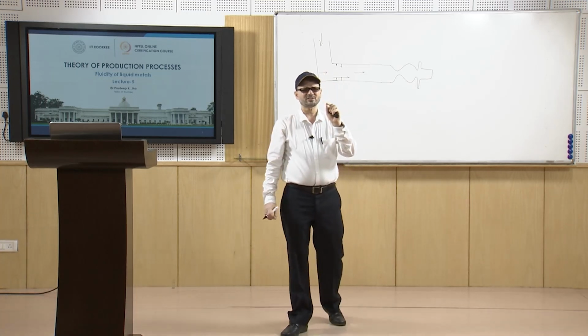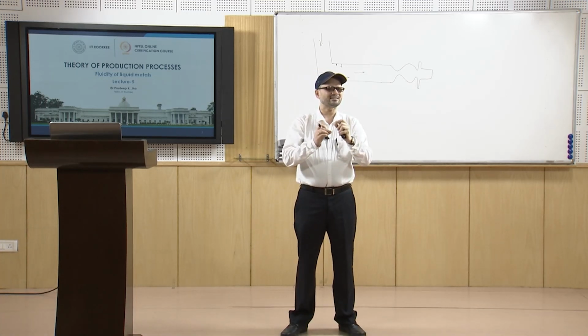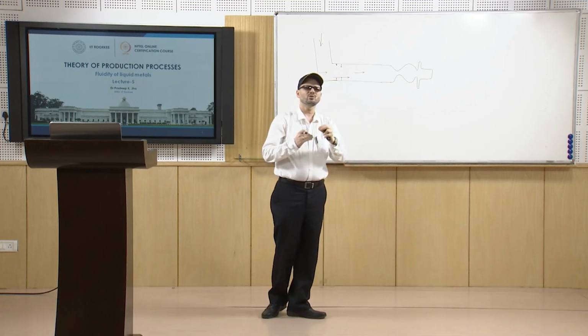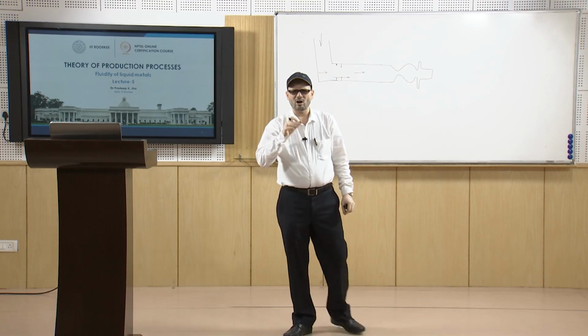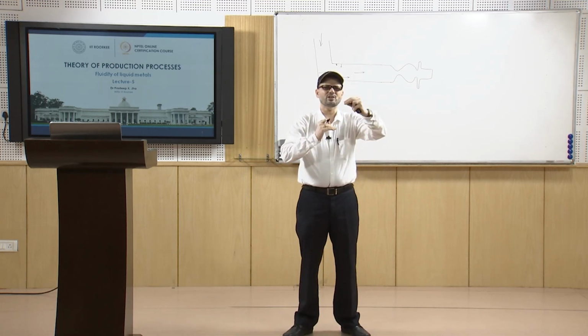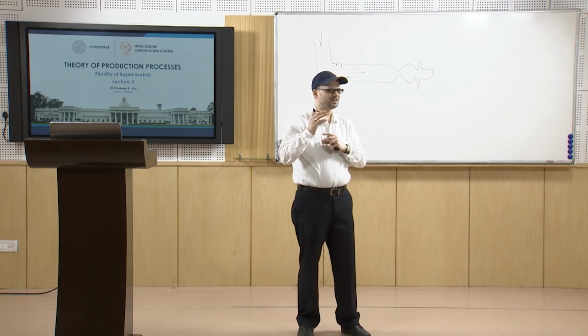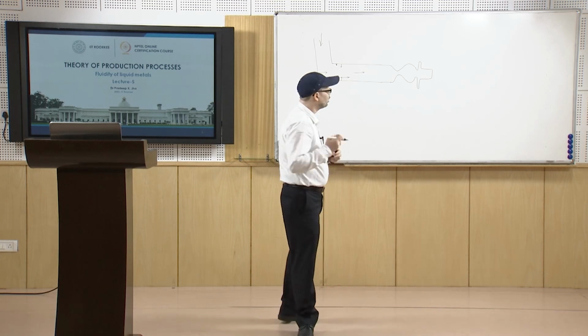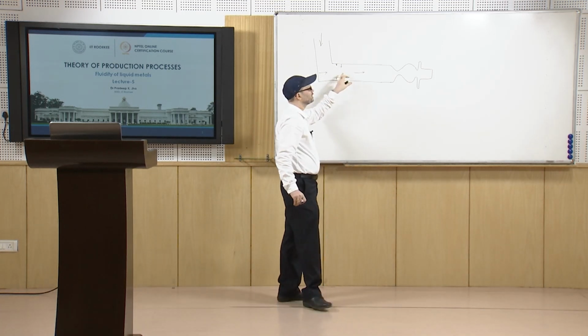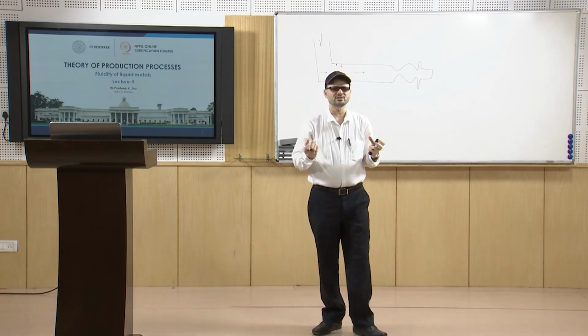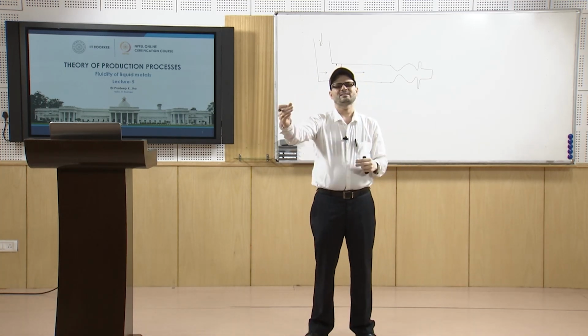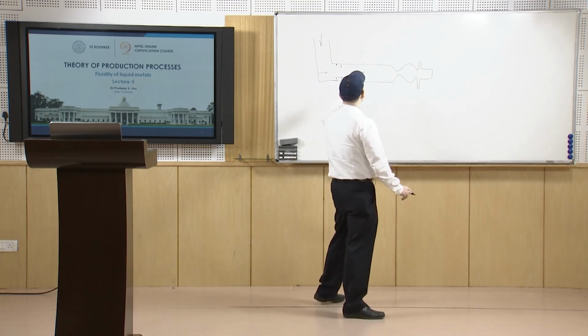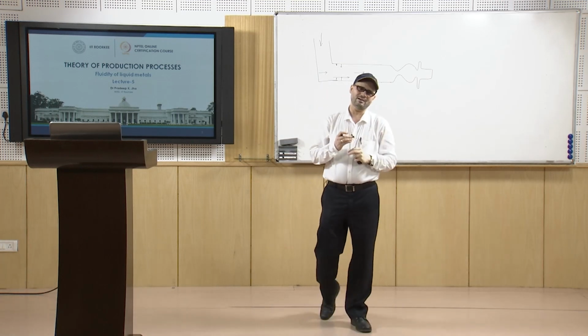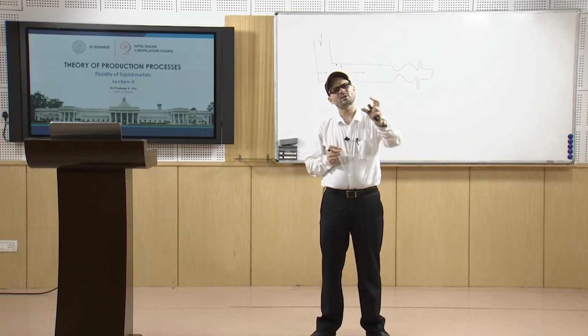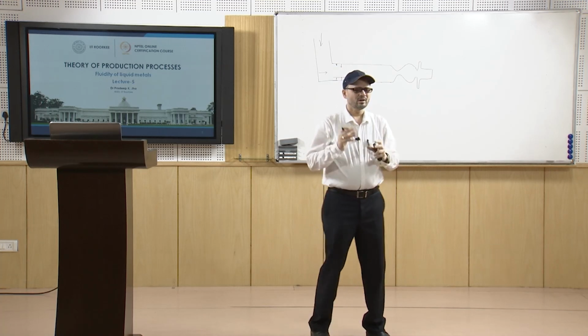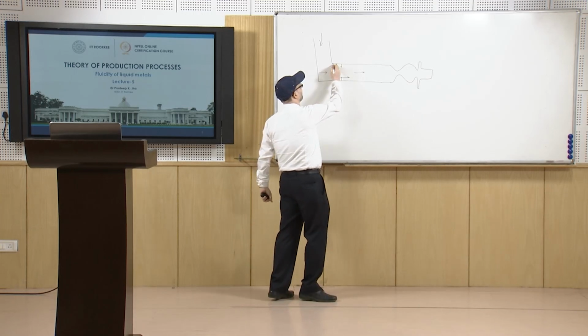If the surface is not smooth, if the surface has a rough finish, like if you are using coarse grains at the layer which is in contact with the liquid metal, it will experience more resistance. The result may be that the liquid metal will experience more resistance, and then it will stop at a small distance. So, you will have to have other conditions favorable, so that the liquid metal goes into all the cavities. Then there are other factors like the design of the gating system.